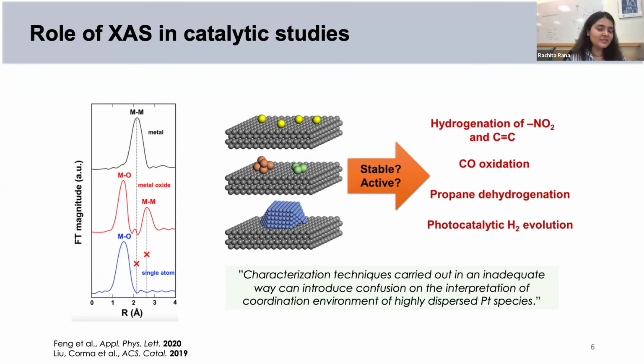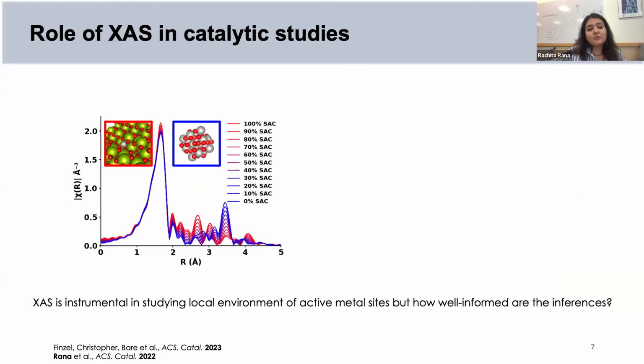And what I want to quote here is this very interesting work from the Corma group, where they said: characterization techniques carried out in an inadequate way can introduce confusion in the interpretation of the coordination environment of highly dispersed platinum species. This was a specific study that they conducted where they used different sizes of platinum catalyst for different reactions. But one of the key points that they were focusing on was the relevance of how you are interpreting the results of the characterization technique that you're using. So that was very important to account for.